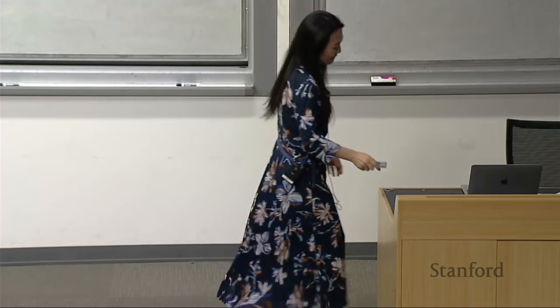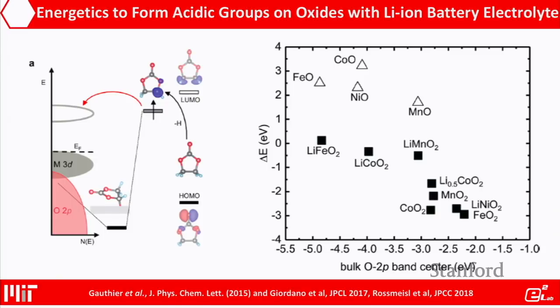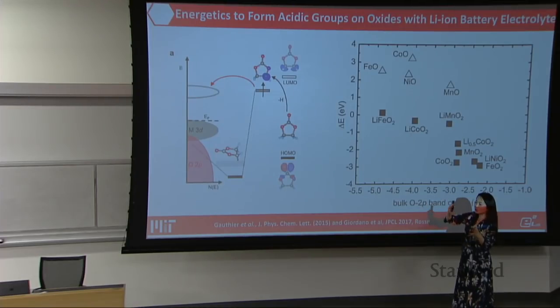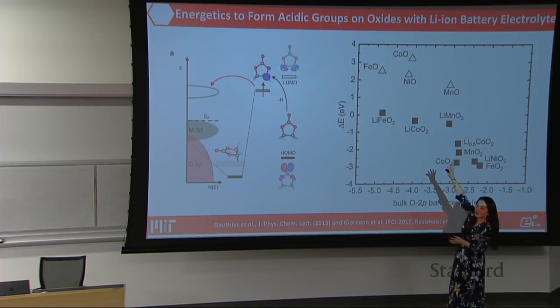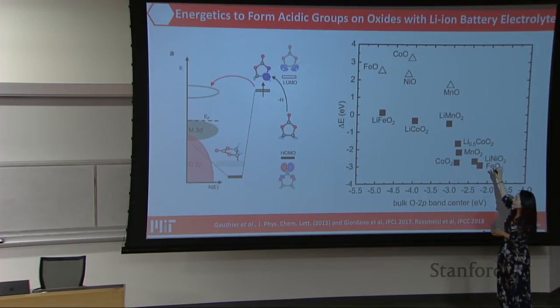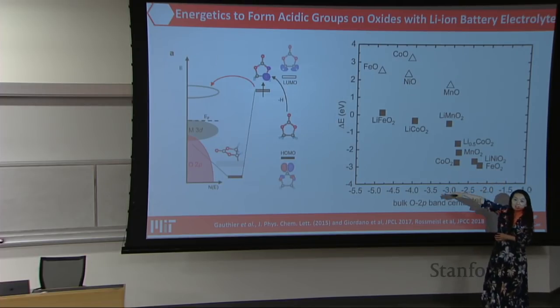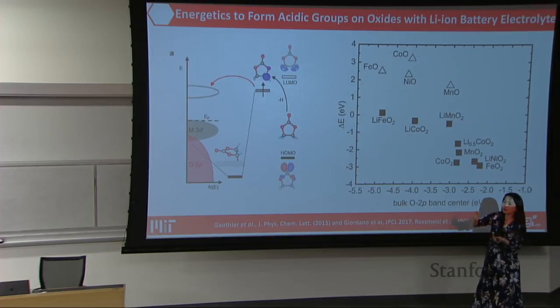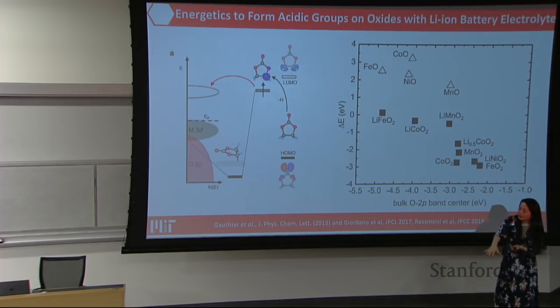so let me just go to this slide, maybe. Let's say 30. So this is a descriptor for stability, right? So essentially, we can think of how to change the electronic structure of a metal oxide surface and decrease the driving force to dehydrogenate the solvent, right? So essentially, we want to have all those rock salt on top. We don't want anybody like this, right? Because here you have a large driving force of negative 3 eV to dehydrogenate, essentially take the hydrogen away from the solvent and generate a proton on the oxide surface, right? So this is, in essence, a design principle for the stability of the oxide surfaces against this particular case.